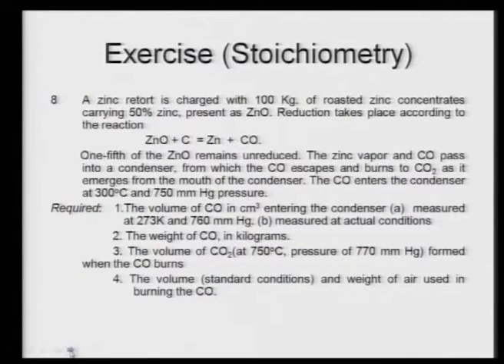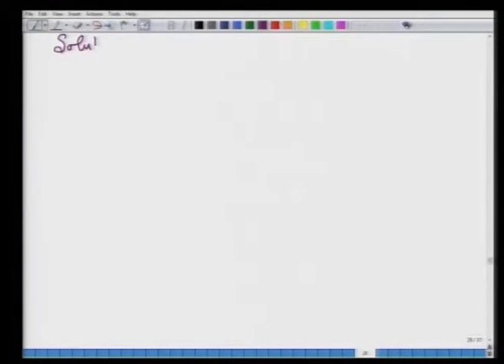The CO enters the condenser at 300 degrees Celsius and 750 millimeters of mercury pressure. So, you have to find out the volume of CO, the weight of CO, the volume of CO2, and the volume and weight of air used in burning the carbon monoxide. These are some of the problems that I am giving to you for solution. Now, let us see the solutions one by one.